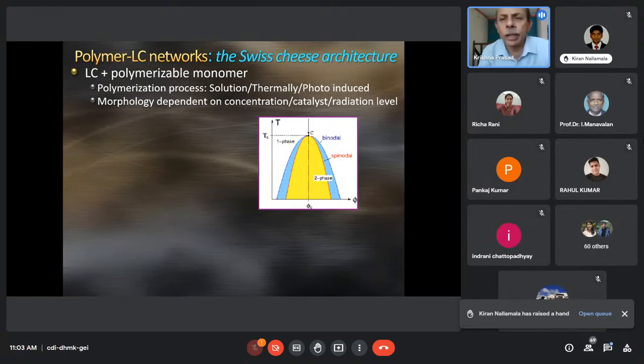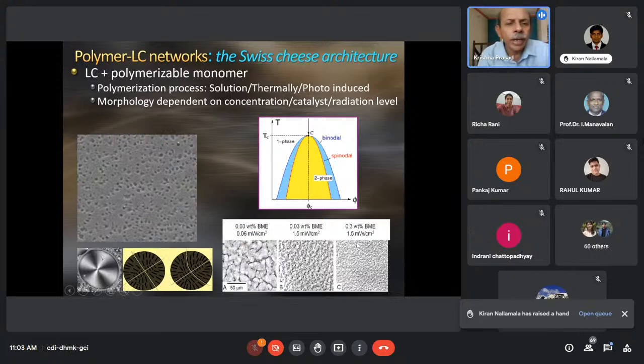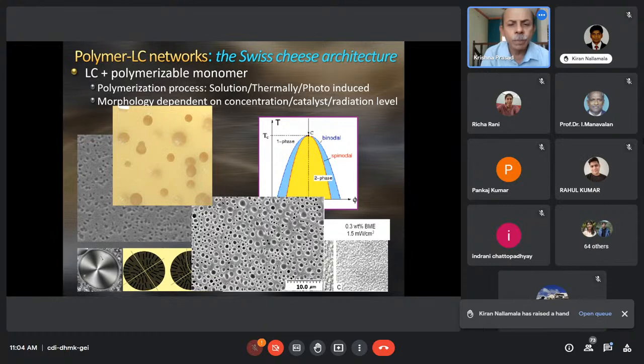And this can be created very simply by appealing to the so-called spinodal or binodal modes when you mix two systems. If over certain concentration ranges they demix, then you create the spinodal or the binodal modes. And that's what is done here. The polymer and liquid crystal generally don't like each other. And so if you can somehow embed liquid crystals in the polymer architecture, then you have a system wherein it is binodal, and at the same time, it creates the right kind of geometry, liquid crystals being confined in the polymer matrix, through which you can apply an electric field and make them switch between scattering and the transparent states. So owing to the kind of networks that can be formed, especially for certain concentration ranges, we call this the Swiss cheese architecture.